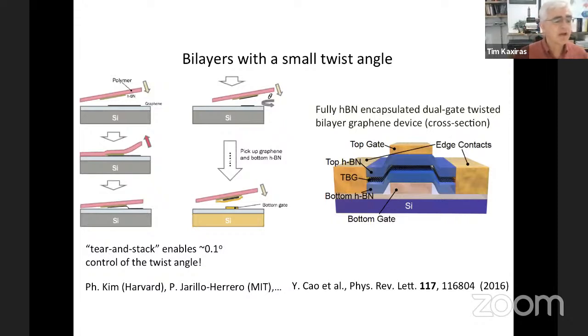I'm sure you're all familiar with this, but just to pay tribute to the accomplishments of our wonderful experimental colleagues who made this whole field possible by putting together bilayers of different layered systems with a small twist angle between the layers. And here's very briefly how they do it. They start with a single layer, graphene, for example, stick something else to it and tear apart half of the layer. And now they know exactly the relative orientation of the two halves.